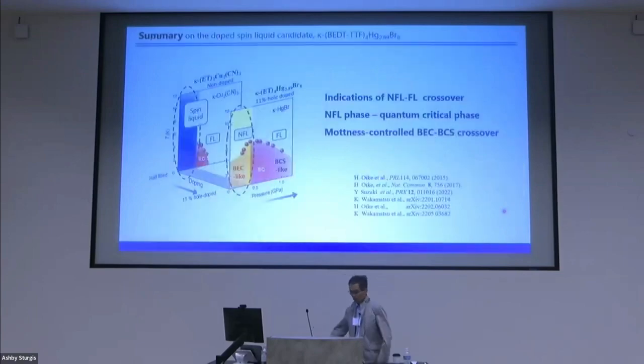Okay, these are the conclusions. In the doped spin-liquid candidate, we observed indications of non-Fermi liquid behavior also, but in this non-Fermi liquid case, the criticality is extended, and then the BEC-BCS crossover was observed. This is a kind of electronic version of the controlled BEC-BCS crossover, because the interaction is tunable in this system.